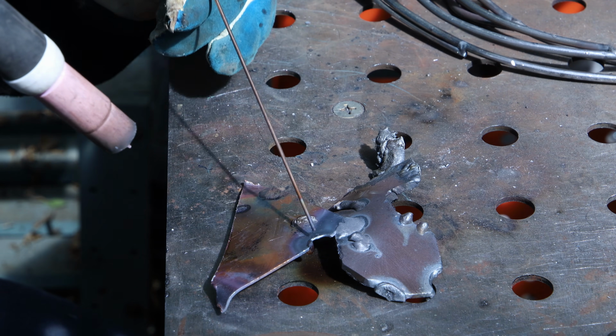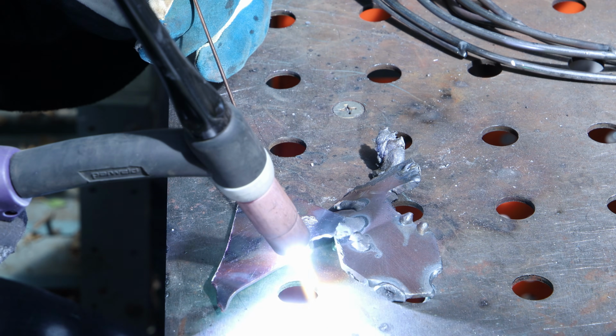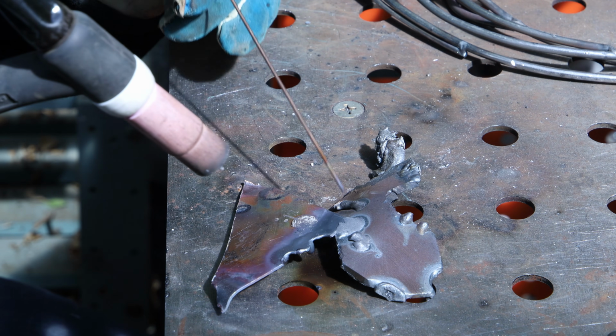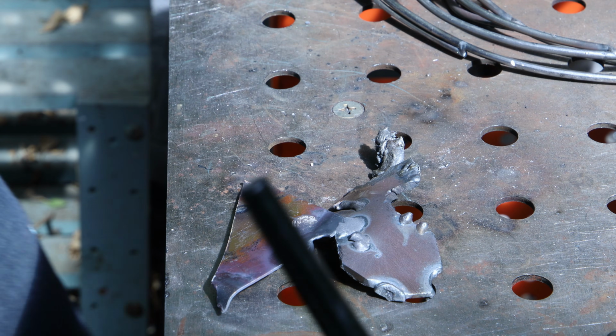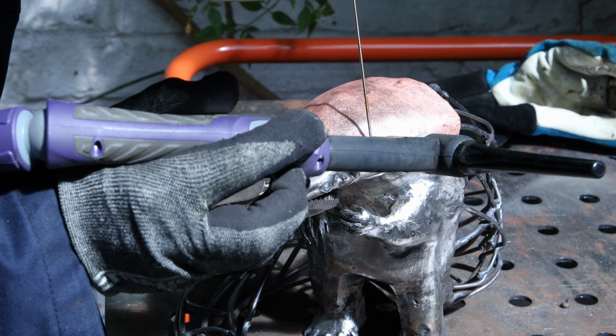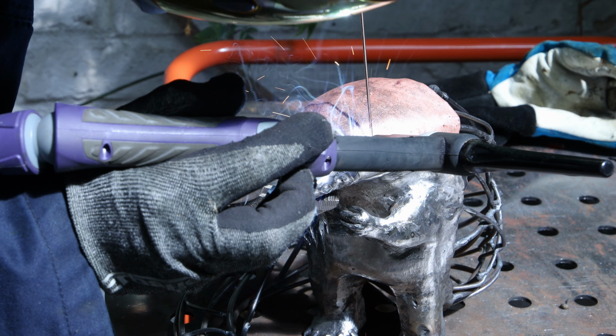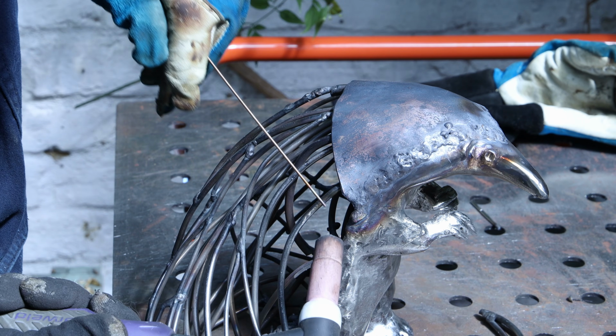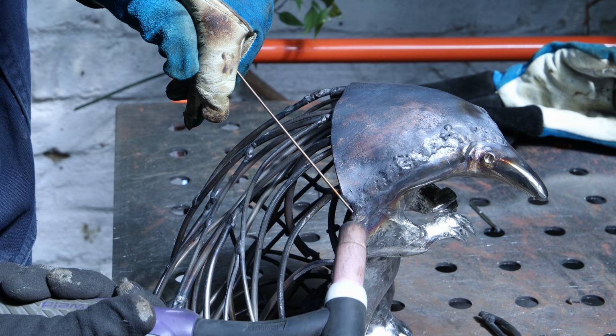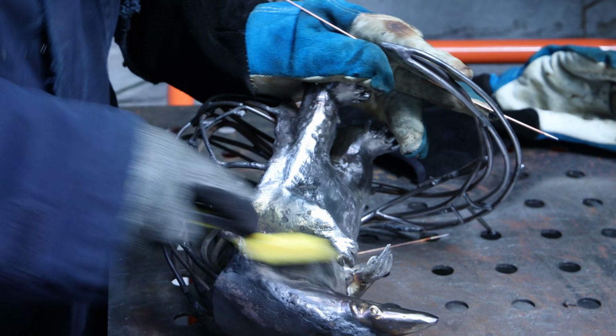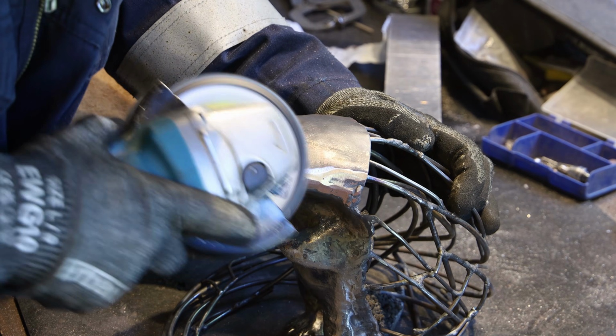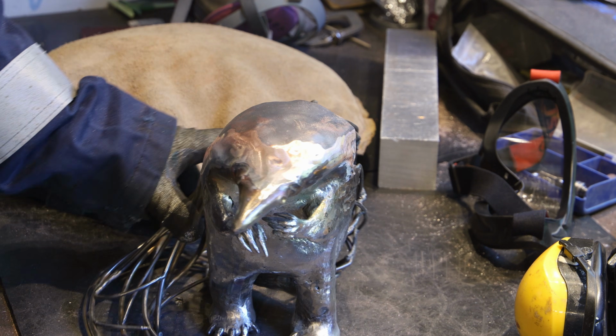Now I'm fully aware of that, but it holds, and that's my priority, because if I only bring the TIG, even on a low amp, look at this, poof, gone. It will melt so quickly. So you have to fight against the melting by feeding more rods. So it isn't about making beautiful welds, it's just about trying to make it work with a very tricky process of welding copper. Now it's not pretty, I'm fully aware of it, but it holds and I can grind it down with a flap disc. Okay, that gave me a good starting point.